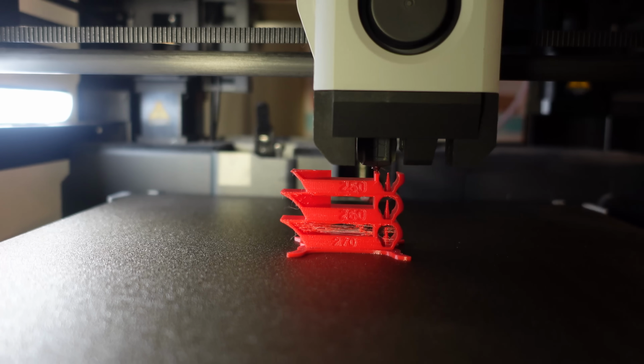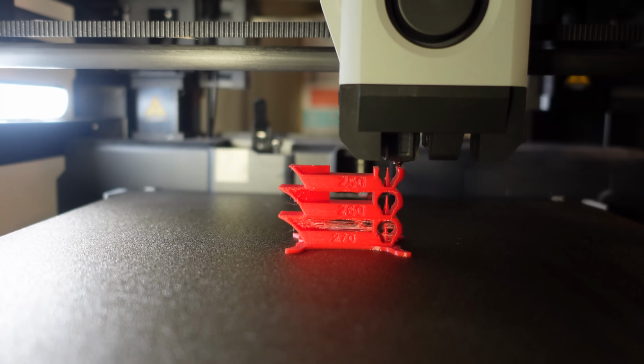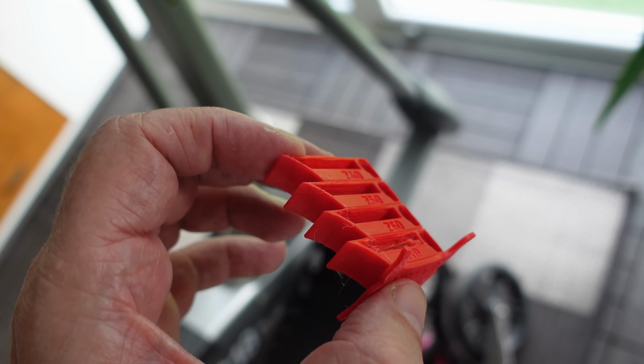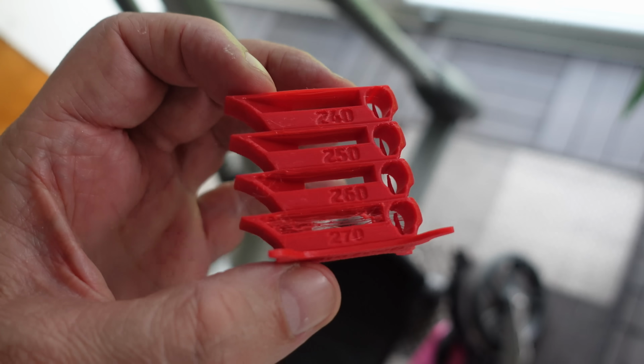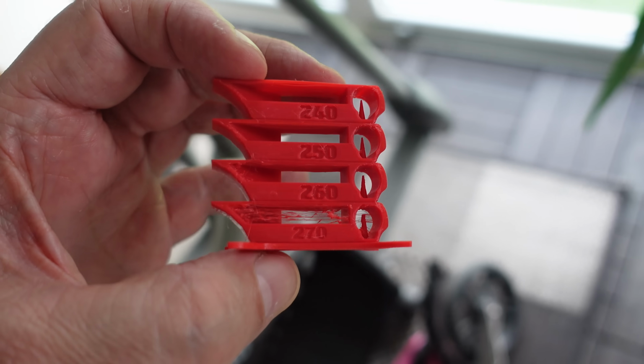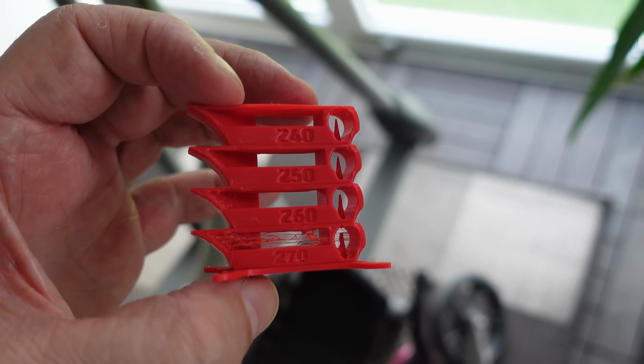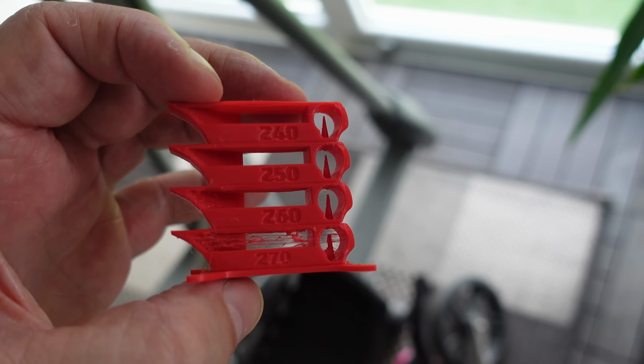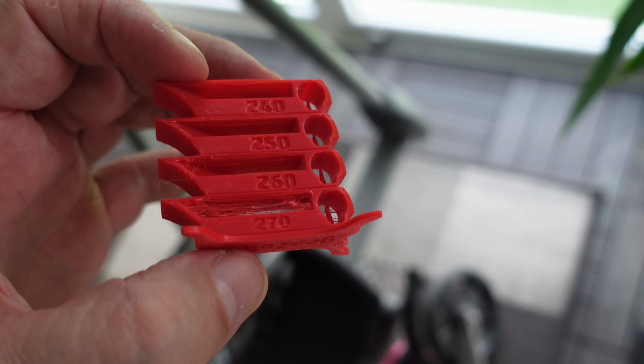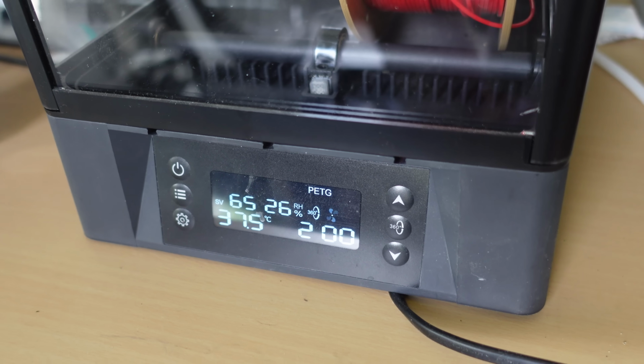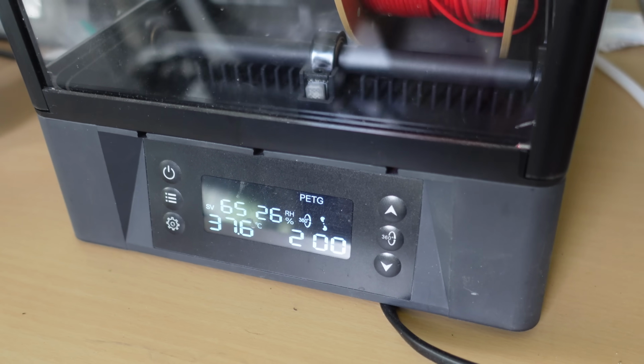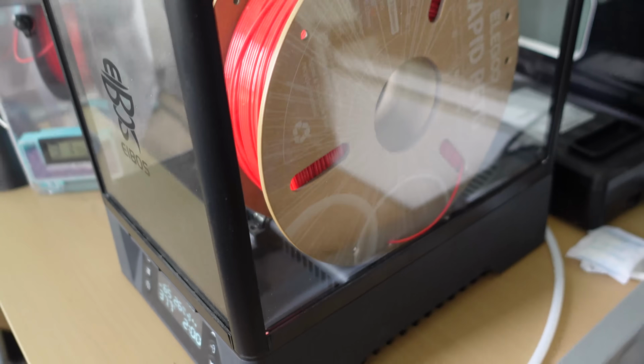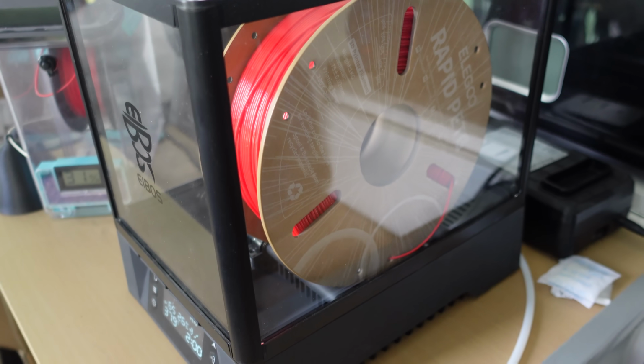The first temperature tower, starting from 270 degrees Celsius. Overhangs are okay on any element, only I can see more stringing on 270 degrees Celsius. Maybe outer loops had some moisture in it, but it will get some drying and then I will reprint this one element. It will be a short drying at 65 degrees Celsius. Usually for the PETG I use 60, but here I can rotate the spool during the drying, so I set it to 65.